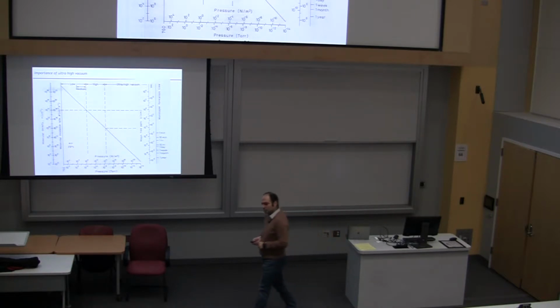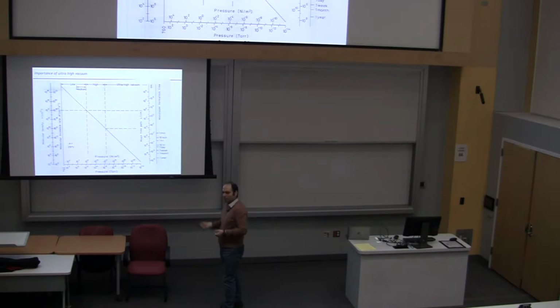What's the lowest pressure achieved in these kinds of chambers? Below 10 to the minus 12, you have to buy a very fancy gauge to be able to measure it, because the X-rays and the neutrons actually interfere with that. Lauren has got 5 times 10 to the minus 13 with a special gauge. But no growth, nothing at the beginning. The moment you turn it on, then you get bad. 10 to the minus 12 is standard, I think.